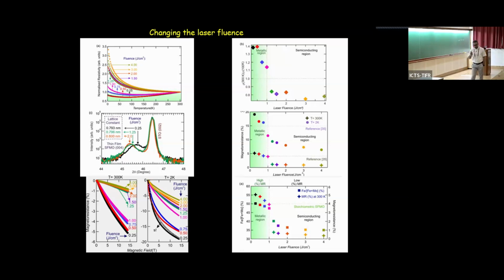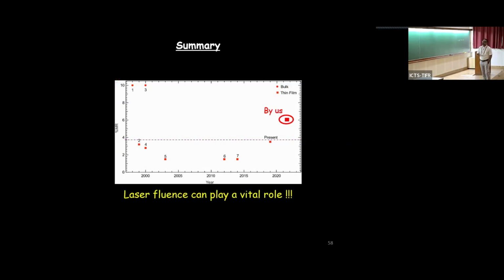We're changing the ratio of iron and molybdenum sites. So it is seen that if you have an iron rich sample, then the system is metallic and you have a high magnetoresistance. Whereas exactly at 50-50 concentration or above that, it becomes insulating and the magnetoresistance decreases. And by changing this kinetics of the growth, we could get around 7 to 8% magnetoresistance in our sample at room temperature, which is much above what people have seen so far for a thin film system. So laser fluence can play a vital role for different physical properties.